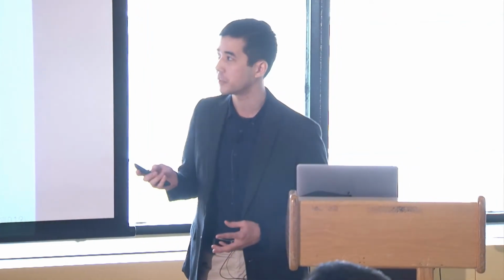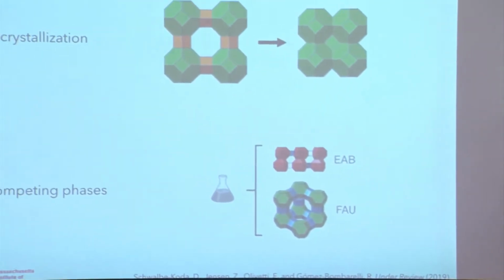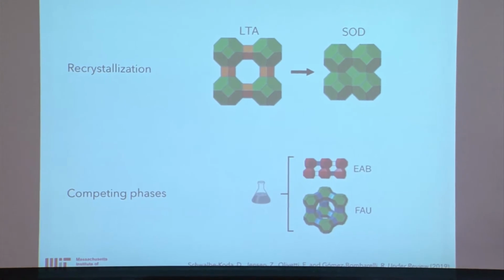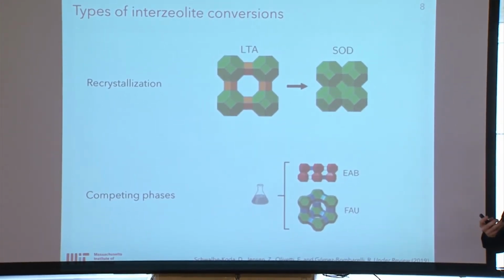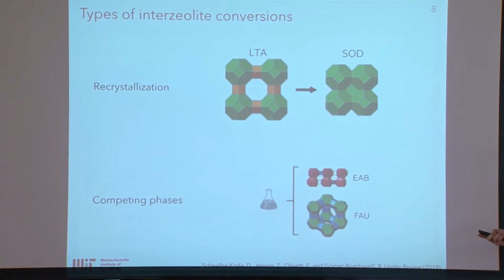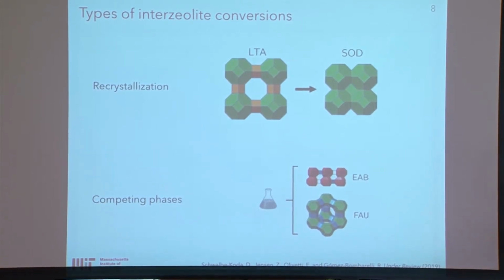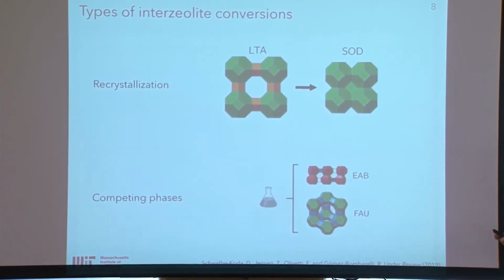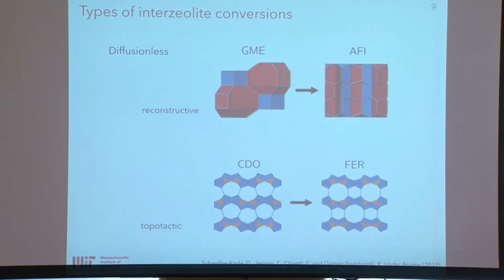So to begin with, what do I mean by transformations? There are certain chemical processes which transform one zeolite framework topology into another. For example, recrystallization processes, usually based on hydrothermal treatments, in which you break down a zeolite into smaller pieces and reassemble it into a new framework. A second way of thinking about this is through competing phases, in which 2 different zeolite frameworks are achieved through the same synthetic process. Then we have what we call diffusionless transformations, encompassing reconstructive and topotactic transformations.